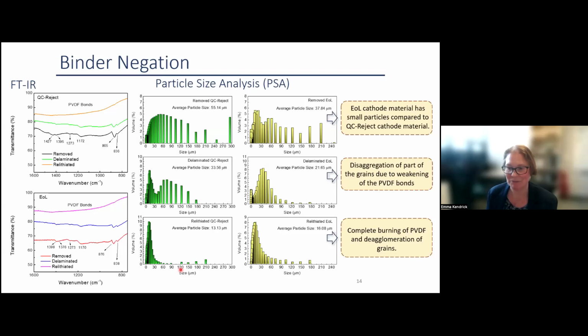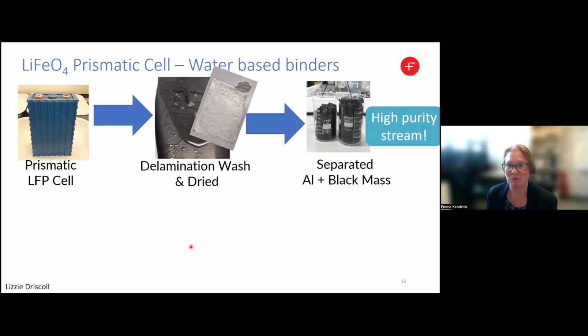We burn it off, it means we're producing HF, which also has been shown to delithiate some of these materials if there's a large quantity around. So ideally what we'd want is something not PVDF that would be removed much more easily. And we can see this as an example in a lithium iron phosphate cell. This is a CALB lithium iron phosphate. In this case, we've separated it and we just use a simple water method to delaminate the material. We can soak it in water, heat it to about 40 degrees and it delaminates relatively easily.